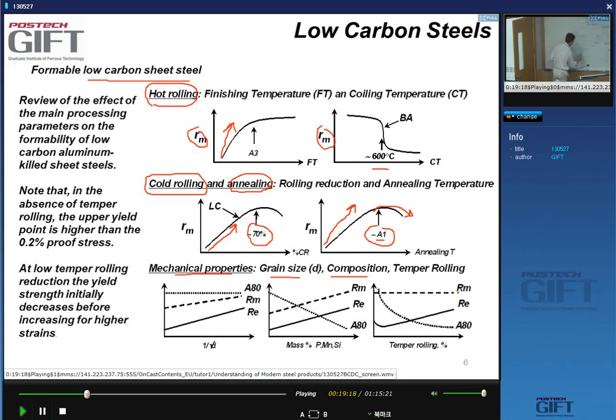Why does the elongation go down? Because in the case of the black curve, the elongation that I could give was this, say if the material breaks here. Now, how much elongation can I give is this one, right? So it's smaller. Obviously, the more you pre-strain the material, the lower the residual elongation you have. That explains this graph in the corner here. So there are many parameters during the processing that will influence formability and mechanical properties, okay?